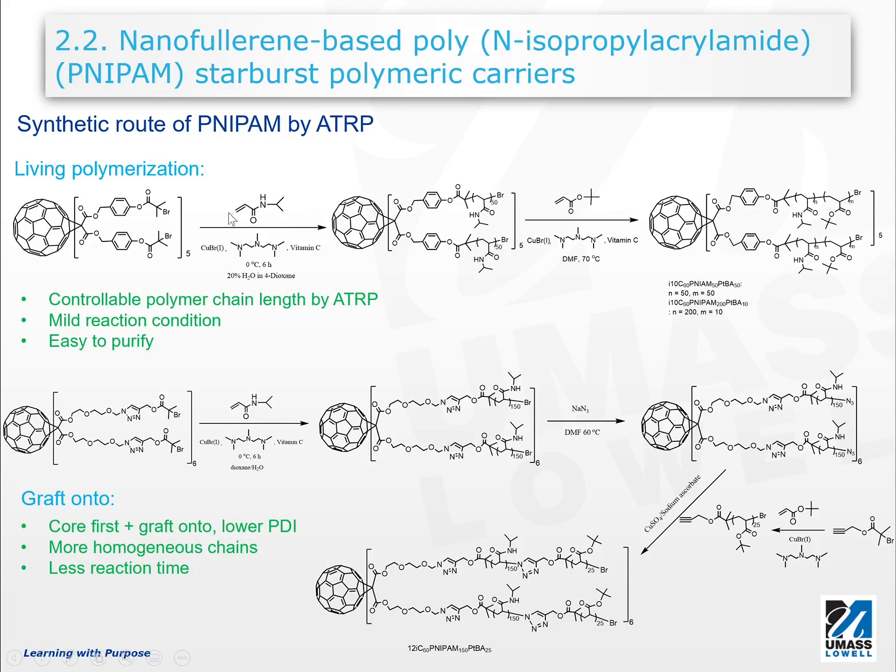First we use the NIPAM monomer to grow the first block of polyNIPAM outside our multifunctional core, and then we continue to grow the tert-butyl acrylate monomer as a second block. So we proved that the polymerization is living and controllable by using our multifunctional core.